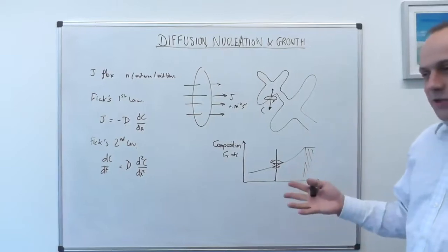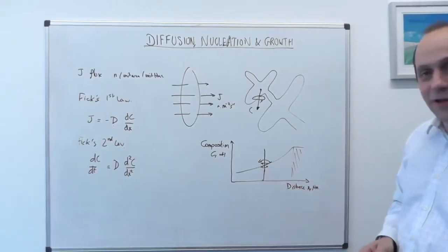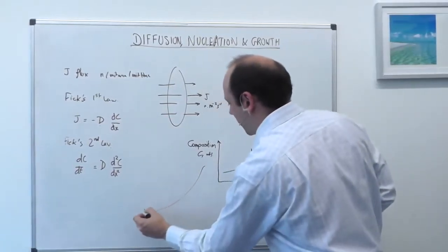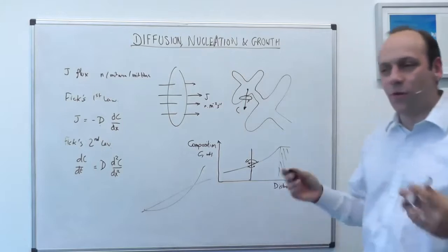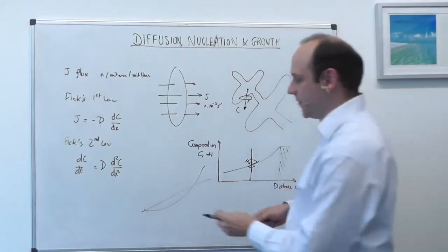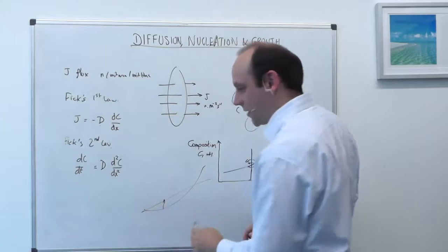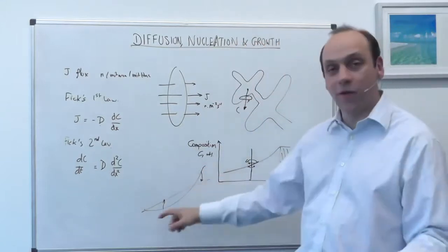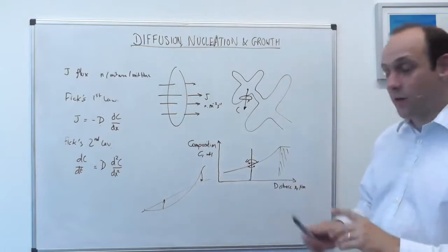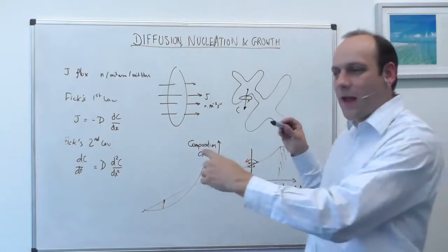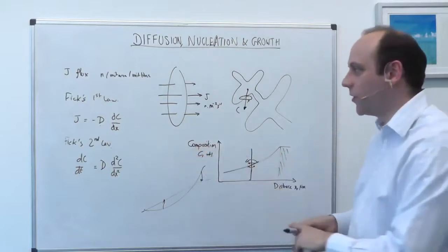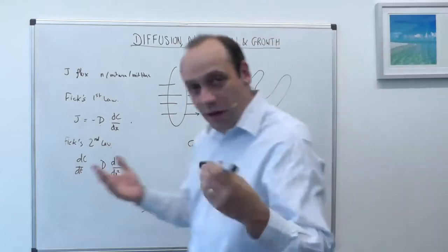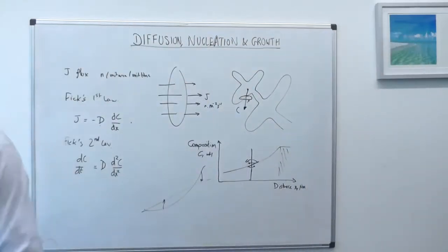So it's, if you like, the concentration flattening rate, how quickly a curve like this becomes a curve like this. This flattening rate, how fast this comes up or this goes down, is proportional to the curvature in the concentration profile, and that's Fick's second law. You'll derive that from Fick's first law by considering the number of atoms moving in and out of a control volume at two different positions. But I'll leave that for 102.